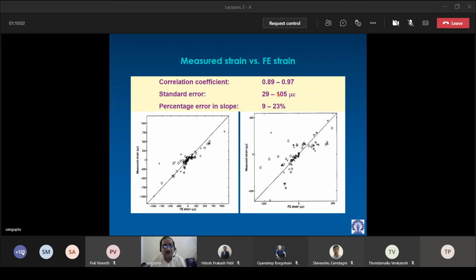Standard error was 29 to 105 microstrain, and percentage error in slope. So when we plotted, we tried to do linear regression analysis to find out the relationship between these two variables, measured strain and numerical FE predicted strain. This is a blowup of the low region of stress, between minus 250 to plus 250, on both sides of zero. Okay, I'm blowing up this and you get this. Of course, there is scatter. This is biological testing compared with FE predictions, but still you can see there is a correlation between these two.